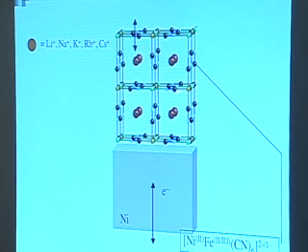In this particular case, this particular iron happens to be 5 angstroms away from the surface, but it's more than 5 angstroms actually away from this iron, a straight distance to the surface. So there could be some sort of a tunneling process. But tunneling doesn't really go very quickly over more than about 10 angstroms. And so, how do the ions out here get oxidized or reduced? So what has to happen? There has to be a self-exchange process.